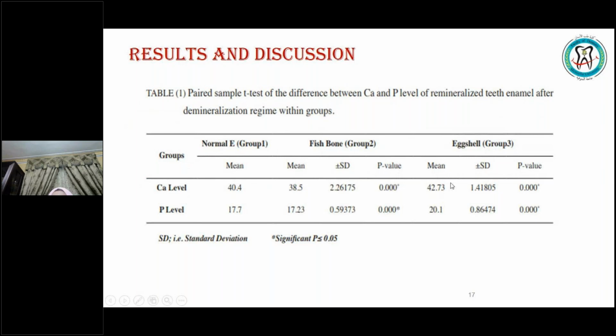Why is it here higher than the normal? We can say it might be due to the demineralization, because the demineralization of the natural tooth has removed a lot of the calcium, and this difference might be due to the demineralization stage or demineralization regime or protocol that has been used before the remineralization protocol of the solution of the study. The phosphorus level was 17 in the normal natural group 1. For group 2, the fish bone, it was about 17.23, and for the eggshell, it was about 20, which is not a big difference, I think.